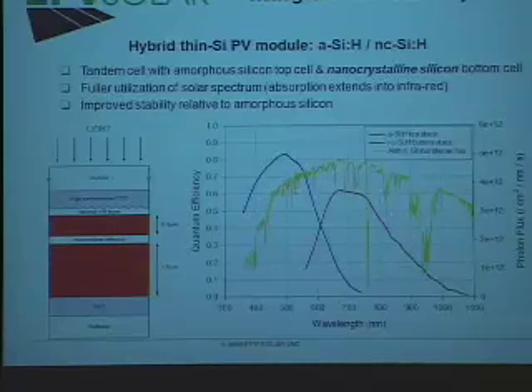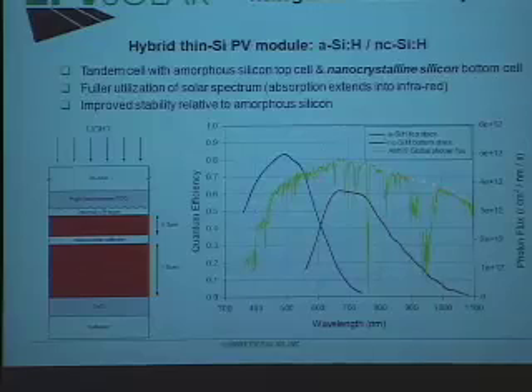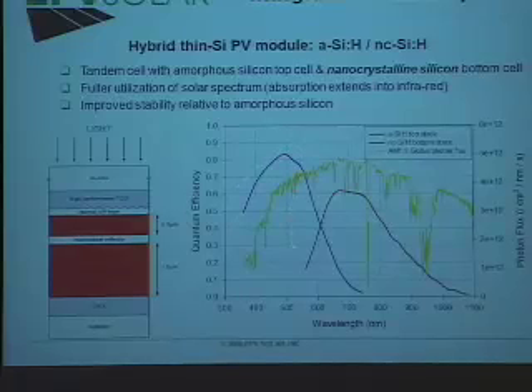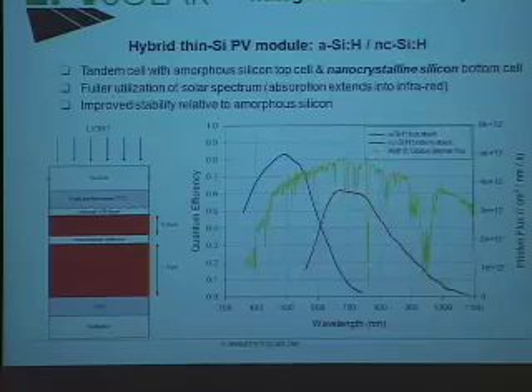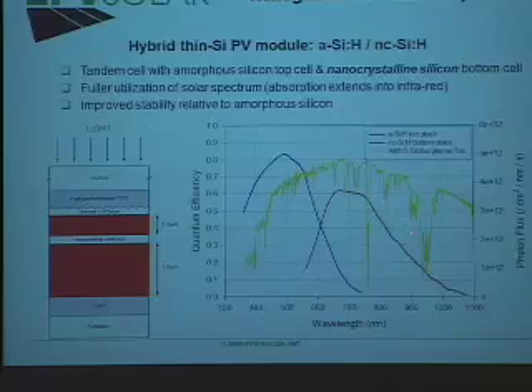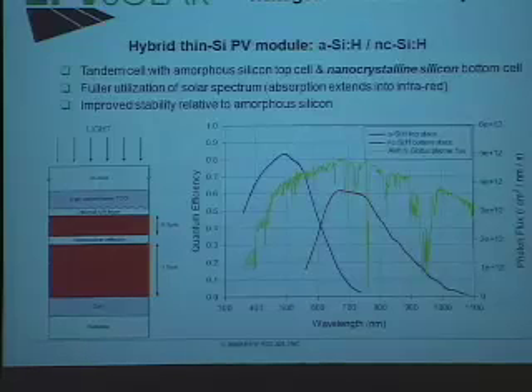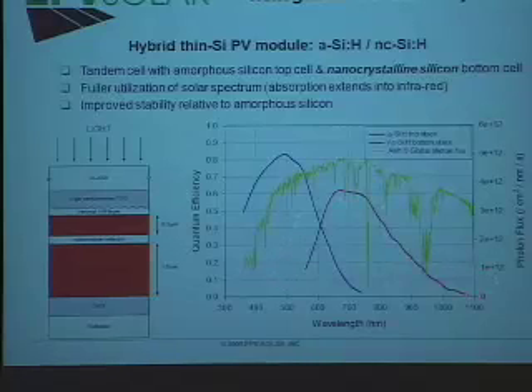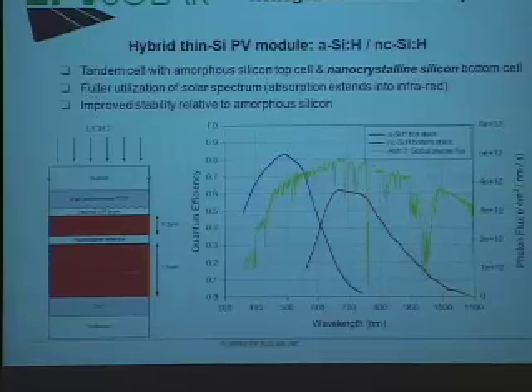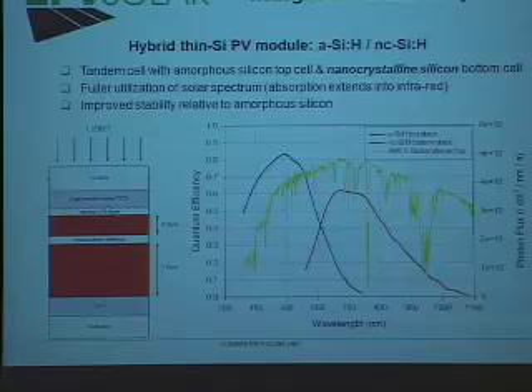This gold trace here is the photon flux from the sun. You can see there are plenty of photons out in the infrared. Amorphous silicon, this is the response of amorphous silicon, cut off at about 700 nanometers. If you add nanocrystalline silicon in the bottom stack of the tandem, now you can extend your response out into the infrared. So this new type of hybrid module, many companies are working on. Oerlikon just had a press release a few days ago, got a new record, 11% module with this configuration. A lot of money being spent around the world on this, and lots of really tough problems to solve.